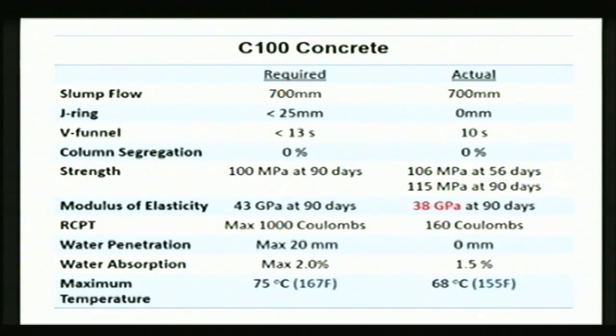The V funnel, less than 13 seconds, 0% column segregation test, strength 100 MPa at 90 days. We agreed with the engineer to be 90 days for the strength. Modulus of elasticity required was 43 gigapascal, and the permeability required on the 1202 was 1,000 coulombs, 20 millimeter penetration on the DIN 1045, and the water absorption, the European test, 2% maximum, and the maximum temperature of concrete was 75 degrees. So these were the actual requirements, and the actual came all right, except for the modulus of elasticity.